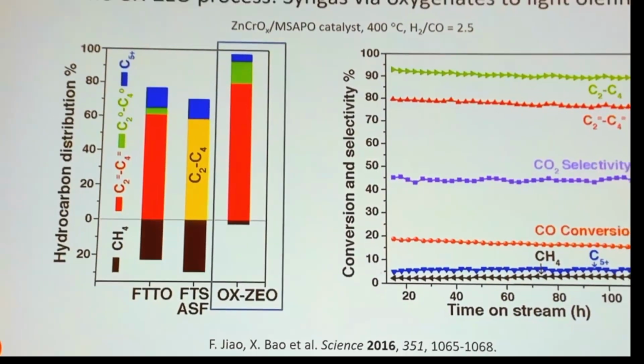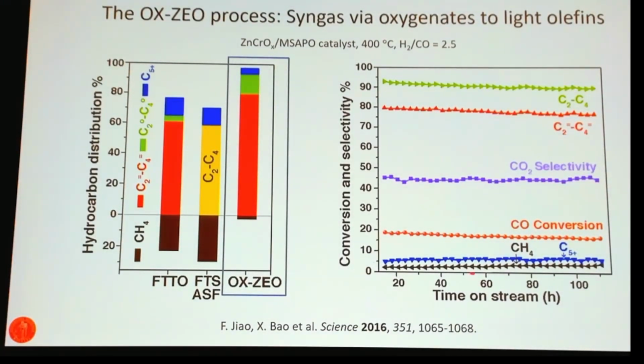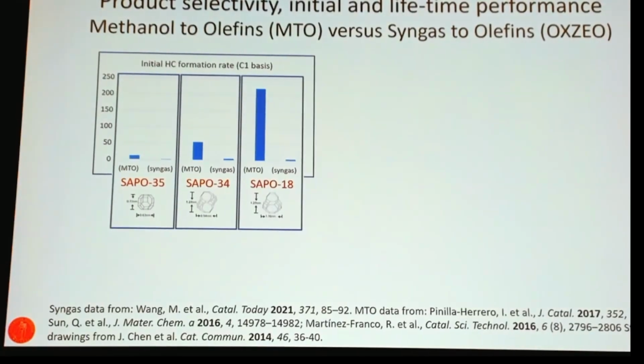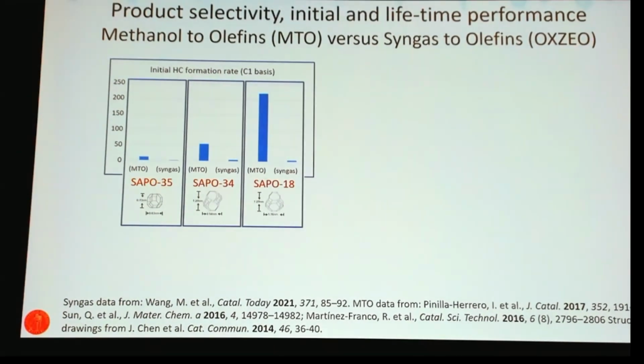We also see here from the same study that over more than 100 hours on stream, there was a very stable CO conversion. So this was encouraging. But we also see that the CO conversion is relatively low in this process. And among the products, we see that 45% of the products are actually CO2. So the question is whether this is now a general feature of the process or whether it's just this study.